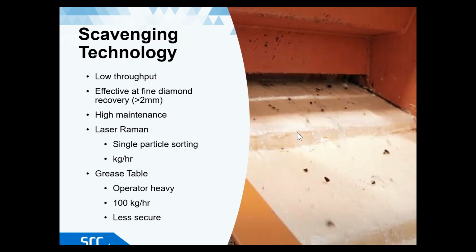Laser Raman, again, is very effective, where it can produce a very clean concentrate where you're only sorting diamonds, but again, it becomes a very slow process, restricting and potentially bottlenecking your circuit.